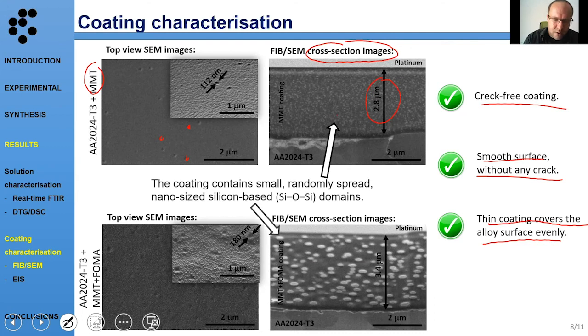micrometers. On the other hand, in the coating with fluorinated acrylates, we can see that these domains are larger, and also they are much more present in the coating. The same if we take a look at the cross section of this coating: we can see the larger size of these nanoparticles, these silicon domains, and also the thickness of the coating increases slightly if the coating contains these perfluoro molecules. From this, we can conclude that the copolymerization has a very important effect on the final coating structure and also composition.